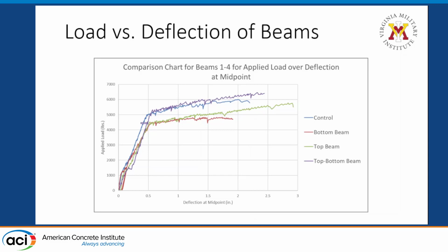It can also be observed that the most ductility is observed on the composite beams with top laminates, and a bottom laminate without a top laminate actually lowers the amount of ductility seen.